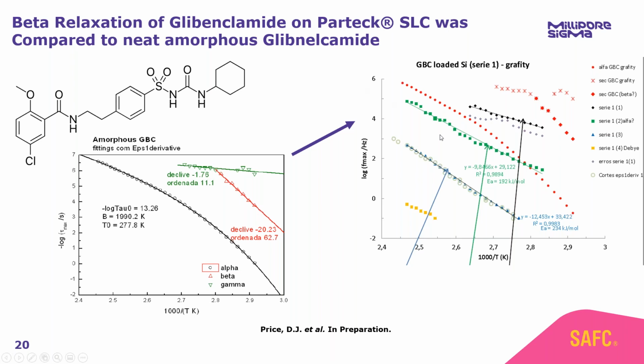However, when we take glibenclamide and load it onto mesoporous silica, our alpha relaxation is substantially reduced, and again, our beta relaxation is almost non-existent. So when we load pharmaceutically relevant compounds onto mesoporous silica, we substantially reduce their molecular mobility. And this reduction in molecular mobility opens up the door to stabilize poor glass formers in pharmaceutical amorphous formulations.